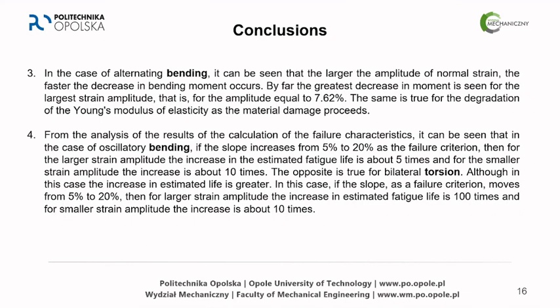And the opposite rule was for torsion, where we had a situation that if the slope moves from 5 to 20%, then for the larger strain amplitude, the increase in estimated fatigue life is 100 times, and for smaller strain amplitude, the increase is about 10 times. So there are some rules which we should think about in the future and wonder why and how to take everything into account.